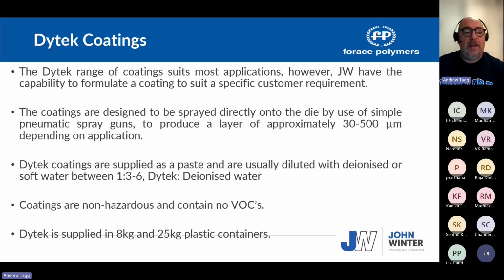Only yesterday, from the US, I got a question: would not using deionized water or soft water cause a problem? And I said yes, it could. The minerals in hard water or non-deionized water can react with the binder system and will also leave deposits on the die. The coatings are non-hazardous, only organic with no VOCs, and they're supplied in 8 to 25 kilogram pails.